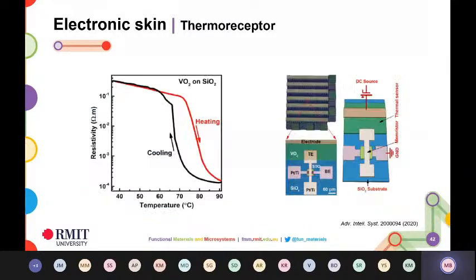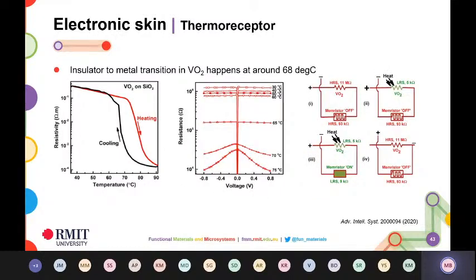A very similar concept for thermoreceptors. This is where our body is reacting to external temperatures. We use vanadium dioxide in this case as a thermoreceptor. The fact that vanadium dioxide changes its electronic characteristics on heat is what we use to demonstrate the thermoreceptor characteristics. So again, we connected up the vanadium dioxide thermoreceptors with the brain mimicking strontium titanate memristors, and the two circuits drove each other depending on the external stimulus. What you see in this case is the metal insulator transition usually happens at around 68 degrees centigrade. So while your body does not react for the initial temperatures, once the temperature exceeds a particular limit, it starts reacting to it. And based on how we configure the entire electrical system, the heat being applied on the thermoreceptor changes the resistance states of vanadium dioxide, which in turn changes the resistance states of the memristor.